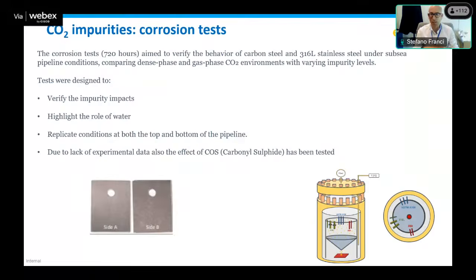And lately, we also want to investigate the effect of COS, which is an issue for some emitters and specifically for cement factories. And so we wanted to test also the reaction with the presence of COS, which, from the literature and from our experience, we don't expect to react and convert to H2S at CCS conditions, but we wanted to test it in this kind of autoclave.